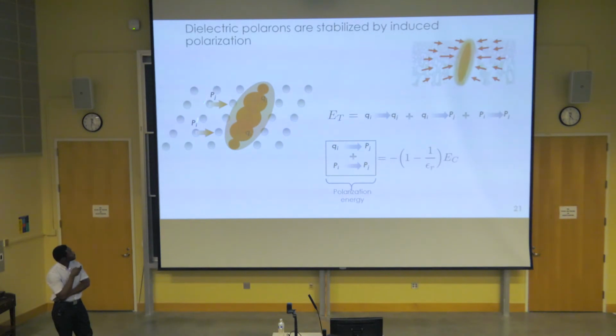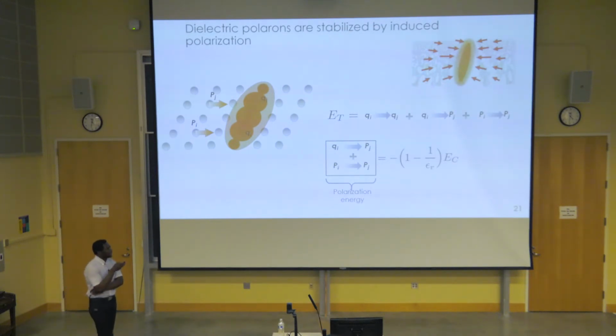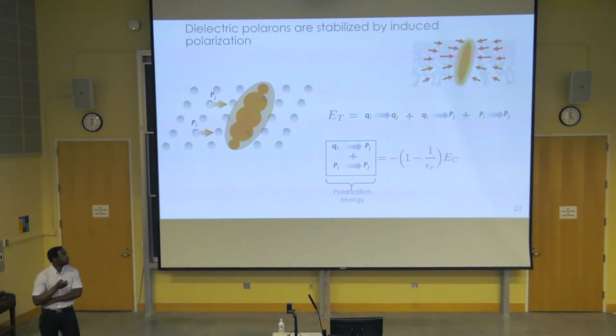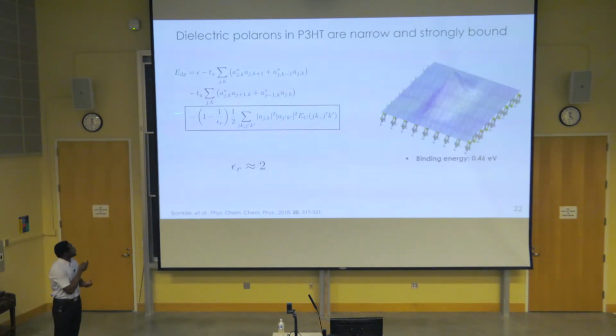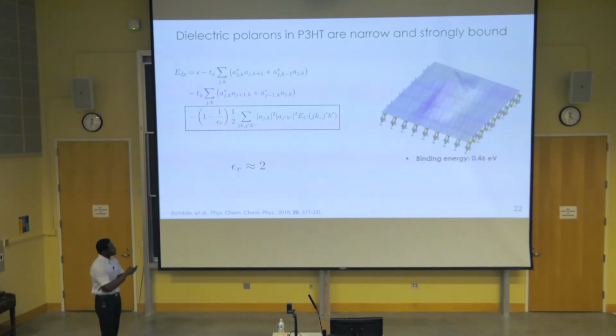However, at equilibrium with respect to the induced polarization, the polarization energy can be obtained in terms of the dielectric constant of the medium and also the interaction of the charge distribution with itself. So this is the dielectric polaron energy we look at. It has two terms: one that wants to spread out the charge carrier, and a stabilizing term, the polarization energy, that wants to stabilize the charge carrier. And here we used a dielectric constant that reflects only the electronic contribution to the polarizability of the